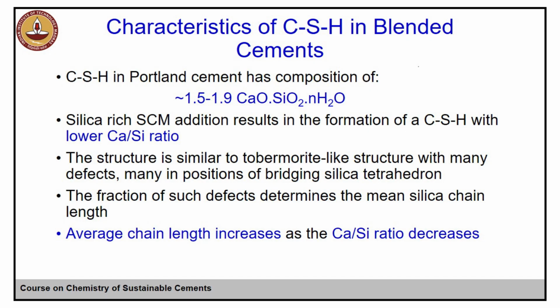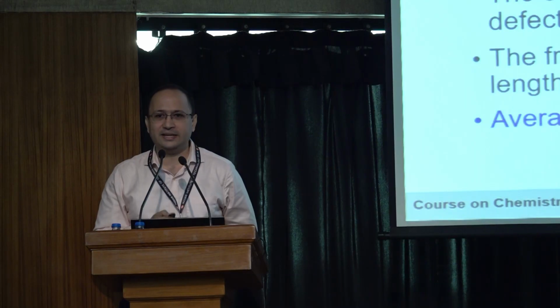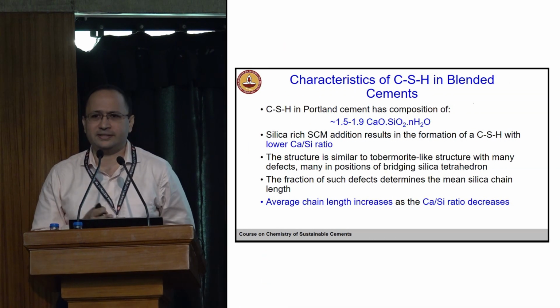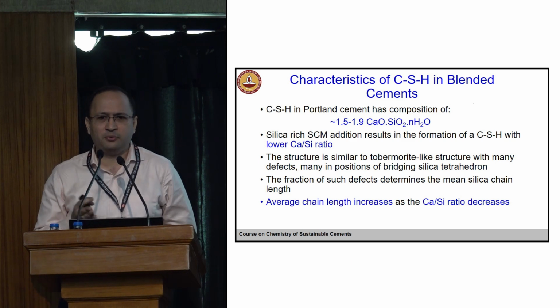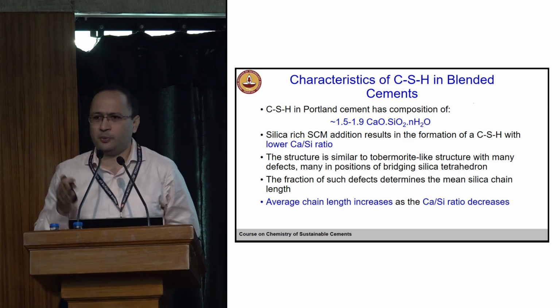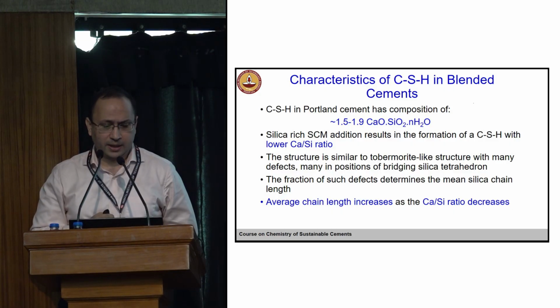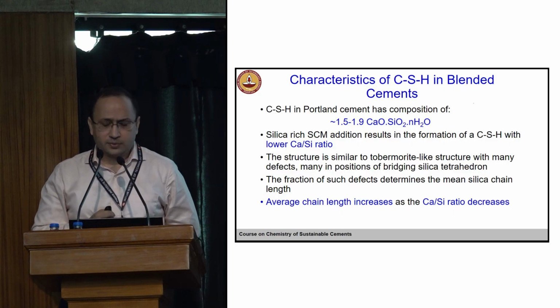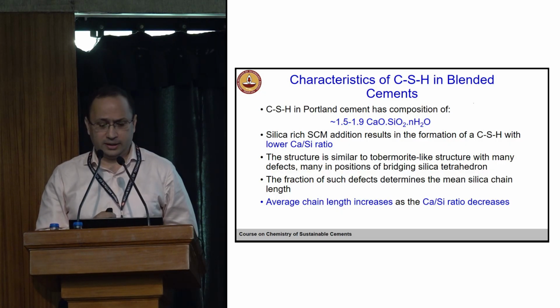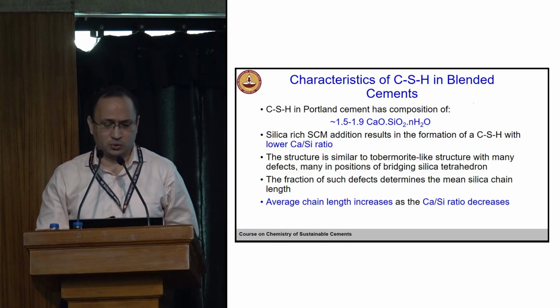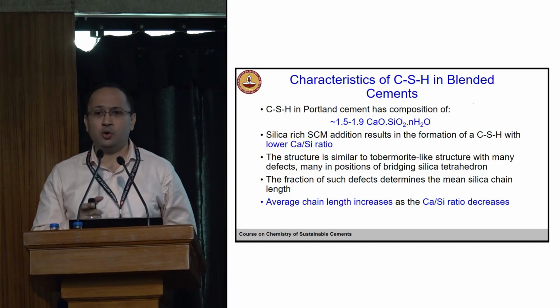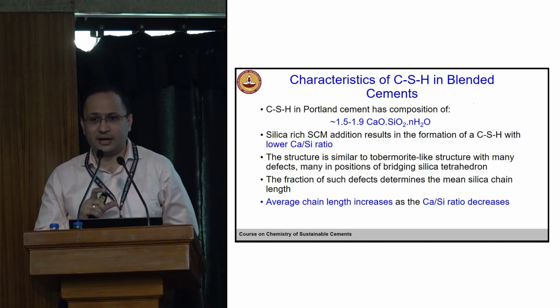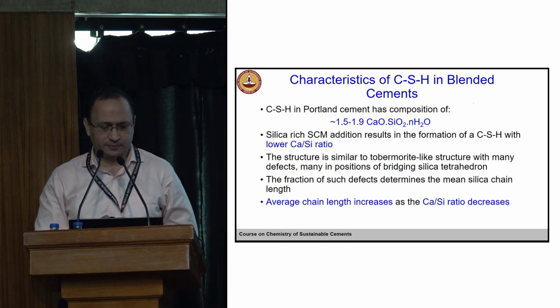So, as we understand, if you look at the hydration of Portland cement, the CSH present in hydrated Portland cement has a roughly C to S ratio that will vary from 1.5 to 1.9, averaging at 1.7. It's not fixed. But what happens when you add silica-rich SCMs? It changes the C to S ratio. It lowers the C to S ratio. Now the CSH which is formed will have a lower calcium to silicon ratio. That's very, very important, that kind of change, right? So it's changing the chemistry.